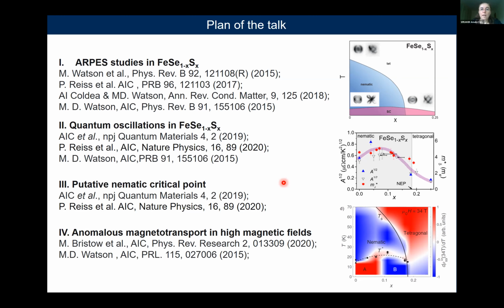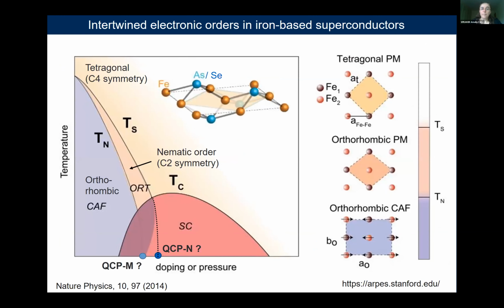So first of all, in iron-based superconductors, we have intertwined electronic orders, in particular the nematic and magnetic orders are the two contenders competing for providing the pairing for the superconducting state. This is a generic phase diagram of an iron-based superconductor where we have a tetragonal phase at high temperature. Then as you cool down, the system goes through a structural transition, and often some of the materials become magnetically ordered in a collinear antiferromagnetic phase.